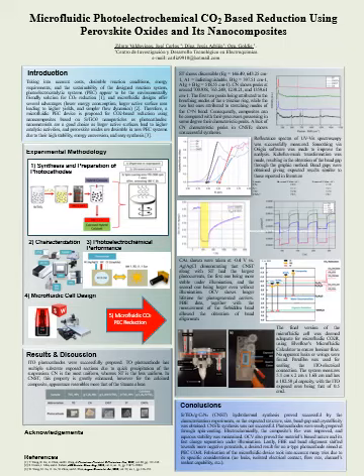After this, the hybrid, the precursors and both hybrid structures were deposited onto ITO via a spin coating process, and following this characterization, photoelectrochemical performance studies were performed. The microfluidic cell design was fabricated, and all of this aimed at successfully reducing CO2 via a microfluidic photoelectrochemical system.